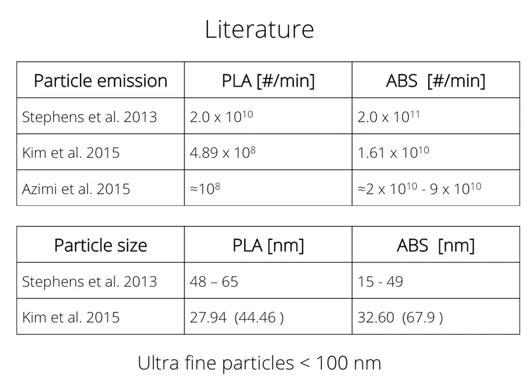However, a newer study now from 2017, Mendes et al., a link to that study is in the description and it's freely available, so you can read through it for free and, well, go for it because it's free. And they showed an interesting measurement because they measured the particle size for ABS in a geometric mean size of 6 nanometers, and if they increased the temperature it went up by 9 nanometers. And this is actually quite an interesting find, and I will get into that later on in the presentation again.